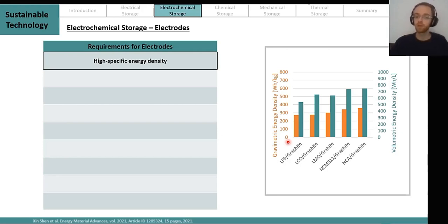For example, stationary energy supply for home. Then we have the LCO, LMO, NCM, and NCA. And I told you that NCM and NCA are basically the high performance materials of today. NCM resembling an 8:1:1 ratio of nickel to cobalt and to manganese, therefore being a very nickel rich material. Now for these, you see that the volumetric energy density is actually very, very high compared to the other materials, and also that the gravimetric energy density is clearly higher than for the other systems I presented.